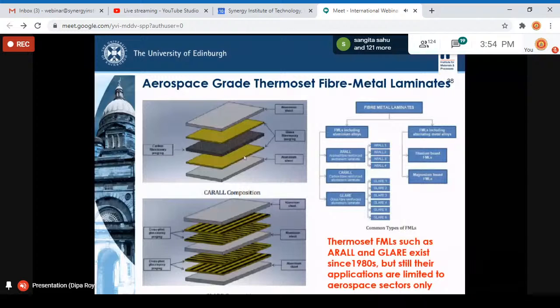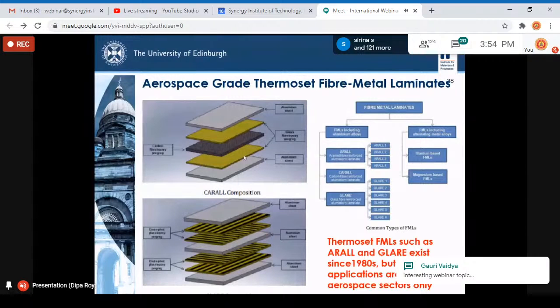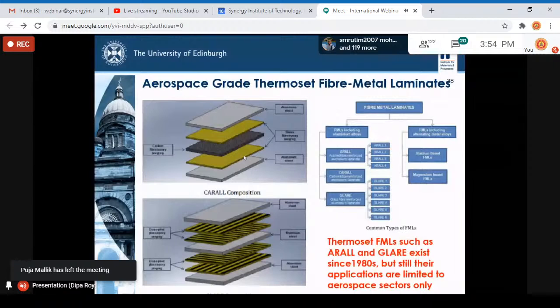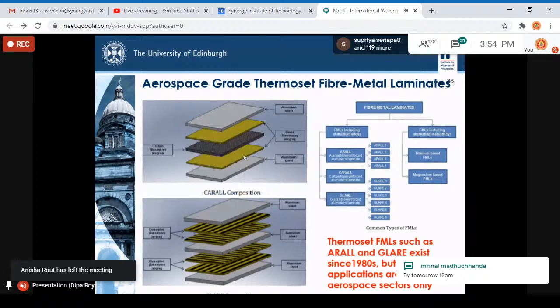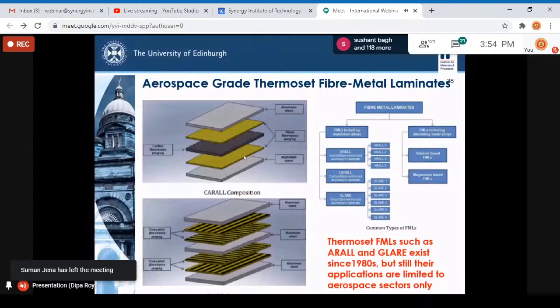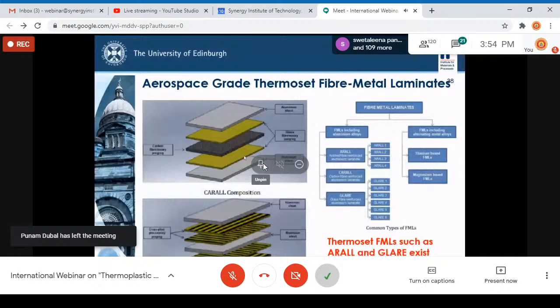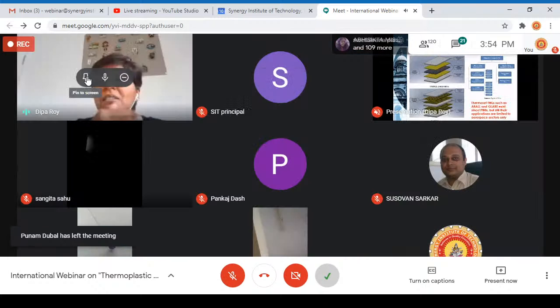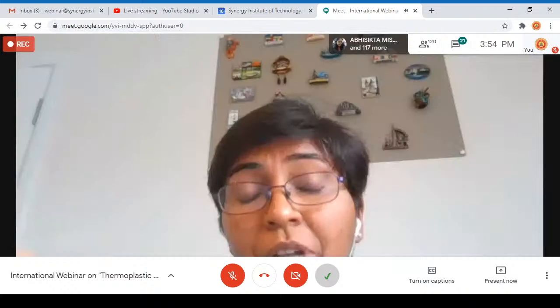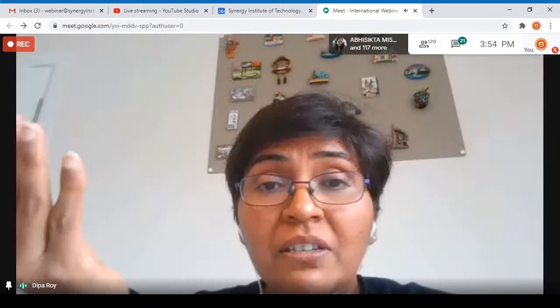So there is absolutely no diversification of the application of these fiber metal laminates because of their cost and their manufacturing. Also, there is another important point to mention. When these hybrid laminates are manufactured, cured normally at about 120 degrees, aluminum has a very different thermal expansion coefficient than the composites. So during this manufacturing, there are also residual thermal stresses at the interface of the composite and the metal. Those residual thermal stresses can act as a point of failure in application during the service life.